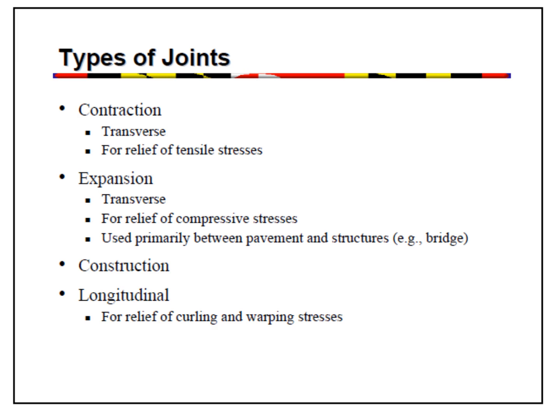Up until the 1950s, it was common practice in the United States to use plain jointed slabs with both contraction and expansion joints. However, expansion joints are not typically used today because their progressive closure tends to cause contraction joints to progressively open. Progressive or even large seasonal contraction joint openings cause a loss of load transfer, particularly so for joints without dowel bars.